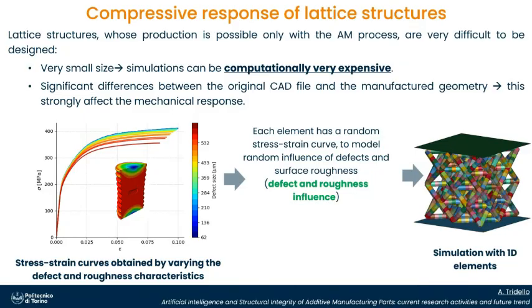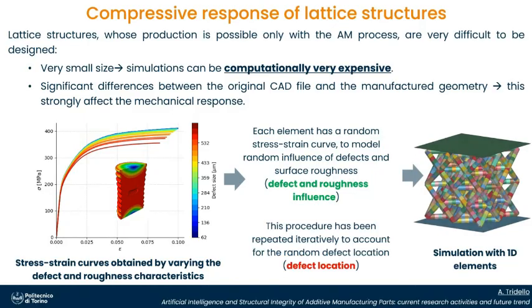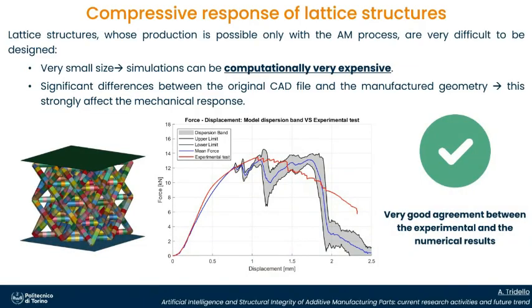We made a simulation with 1D elements, and the procedure has been repeated, varying the position of these elements in order to take into account the random location of defects. We don't know where defects can be at the beginning. So this is the comparison with the experimental data, and you can see that we obtain a good prediction. And we have a scatter range of the curve due to the presence of defects.